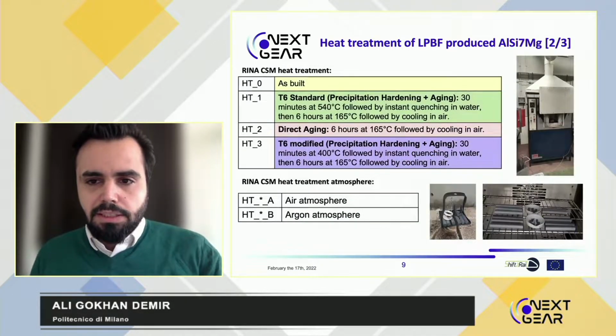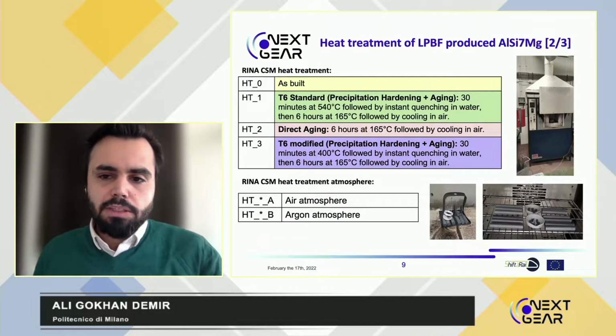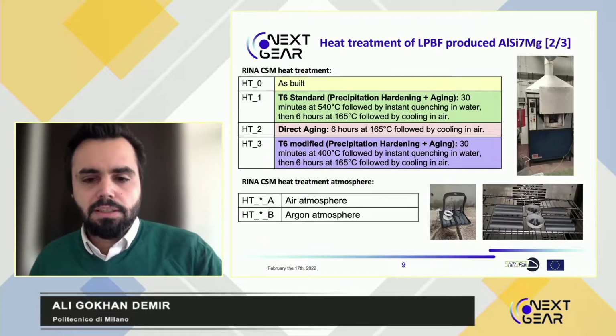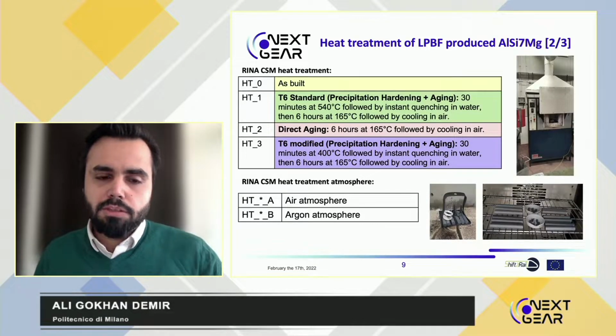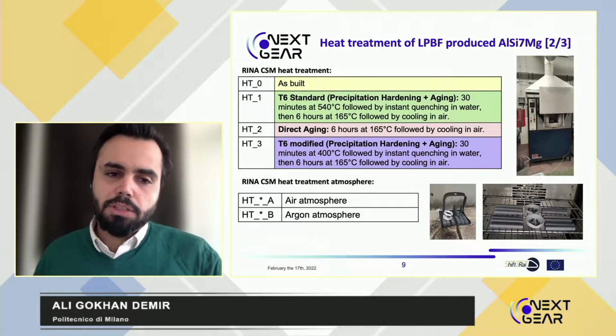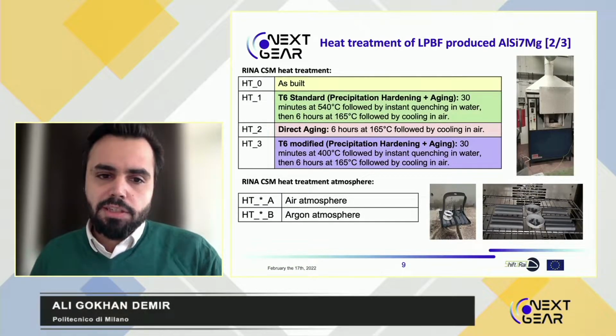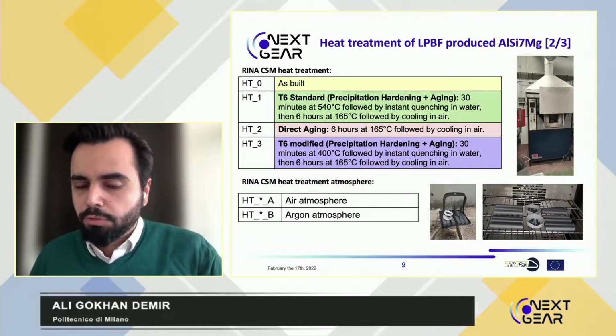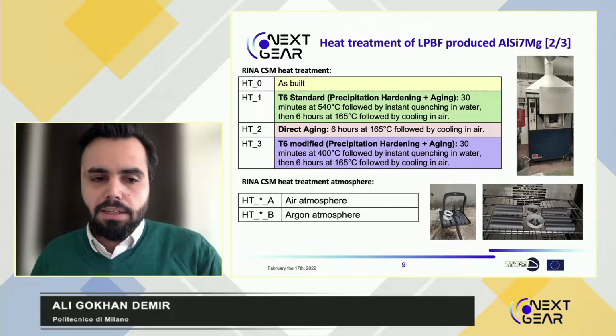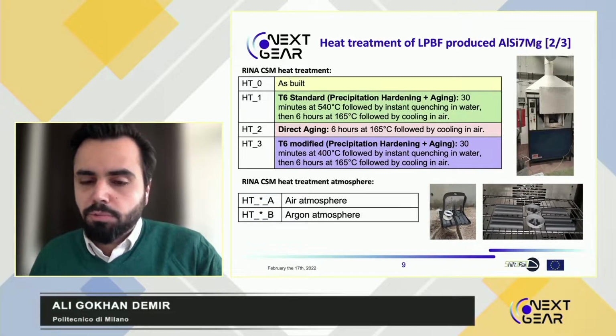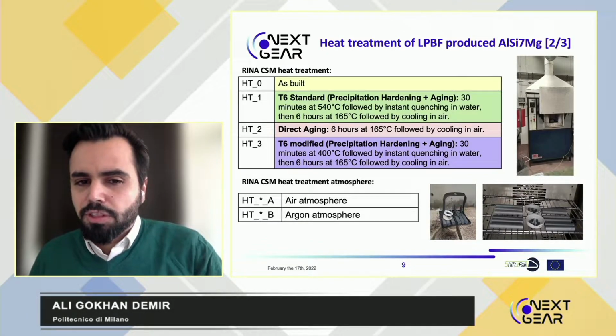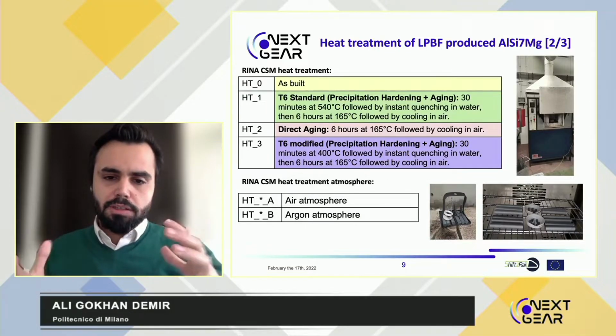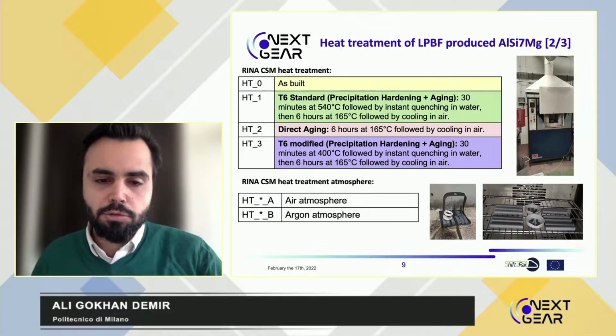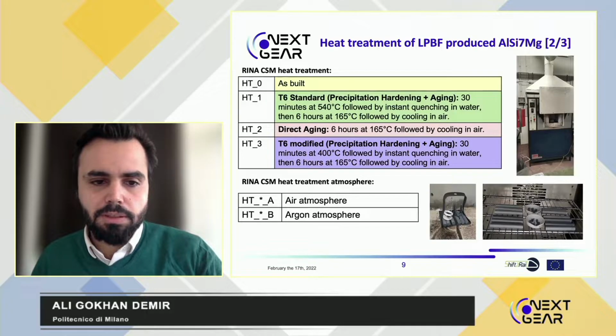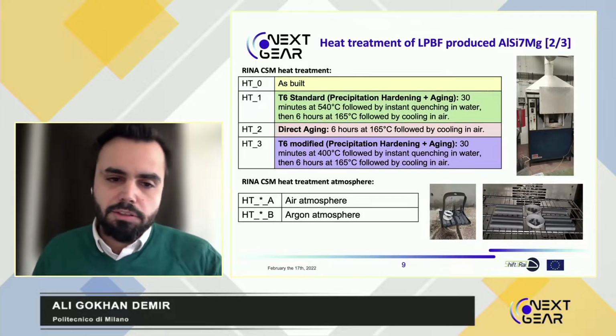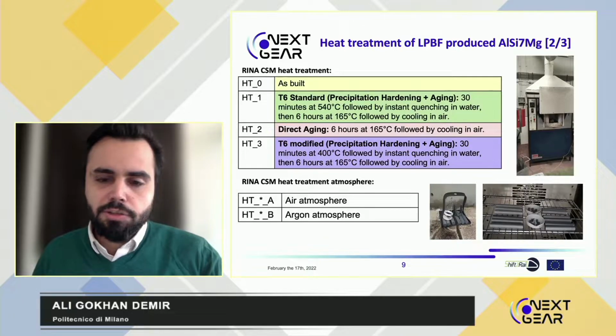Going quickly into the details, my colleagues in Rome, together with us, studied the heat treatment options, starting from a standard aluminum alloy heat treatment, that is a T6, the standard heat treatment which could be applicable to conventional aluminum alloys. It considers a quenching process in water, which might be also somehow detrimental for large parts, as that might bend and get distorted during this part. They also considered a direct aging treatment and a modified T6 treatment.